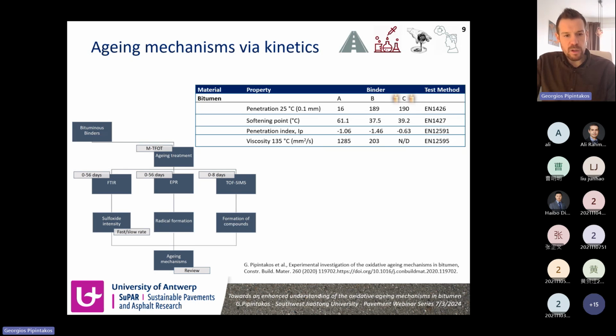For example, a Fourier transform infrared spectrometer, or FTIR, electron paramagnetic resonance, or EPR, and time-of-flight secondary ion mass spectrometry, or TOF-SIMS. The idea of these three techniques was that we were trying to probe, of course, the hypotheses for the aging mechanism: the formation of sulfoxide that was reported by the SHRP report and Petersen and his colleagues in the 60s, the formation of radicals, as I mentioned, when the hydroperoxide is unstable, and also to understand what other chemical compounds can be formed.